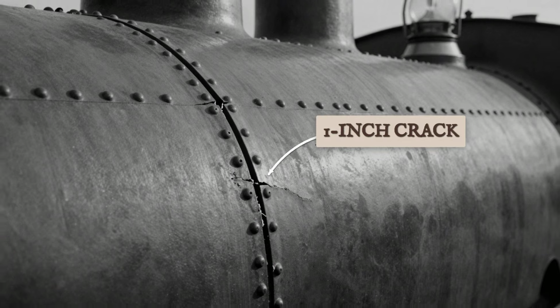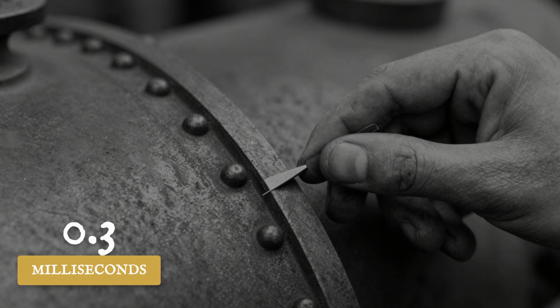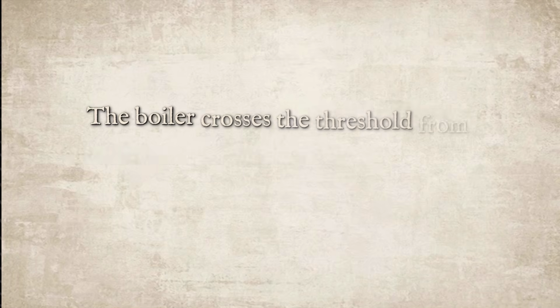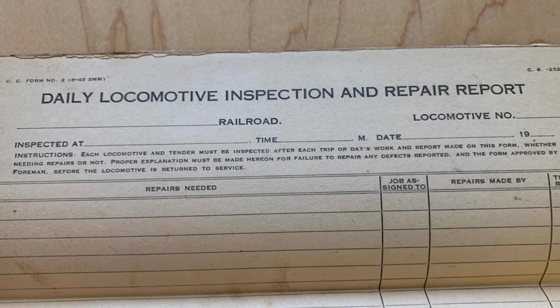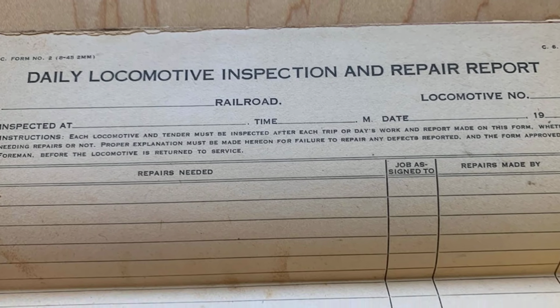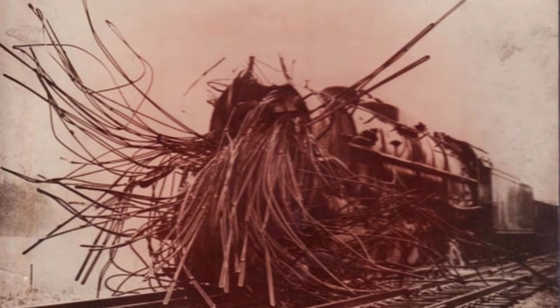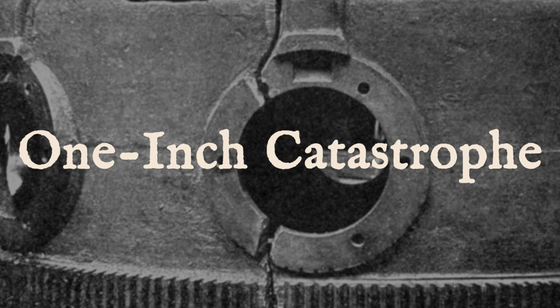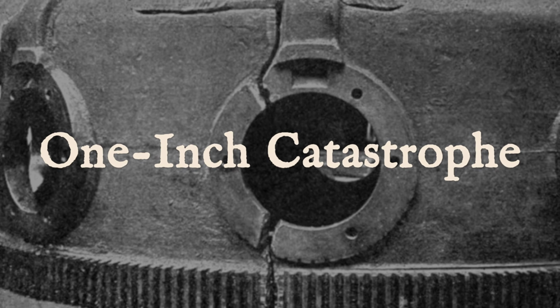A 1-inch crack is all it takes. The margin for error is measured in the thickness of a fingernail. The boiler crosses the threshold from machine to weapon in less than the blink of an eye. The paperwork, the warnings, the deferred repairs all vanish in the white flash of uncontained mechanical failure. A 1-inch crack at the staybolt root is not a defect. It is a firing pin.